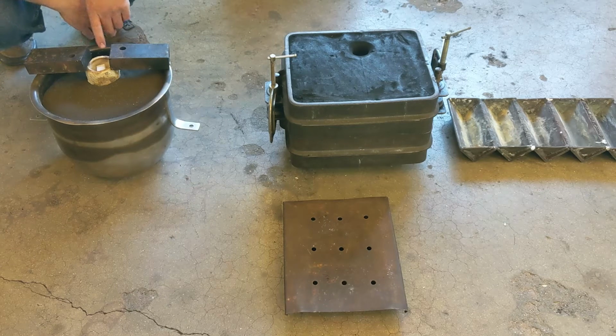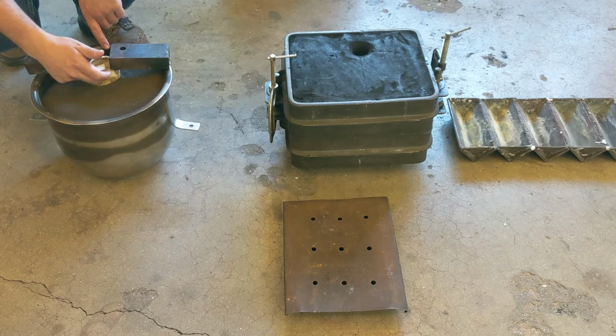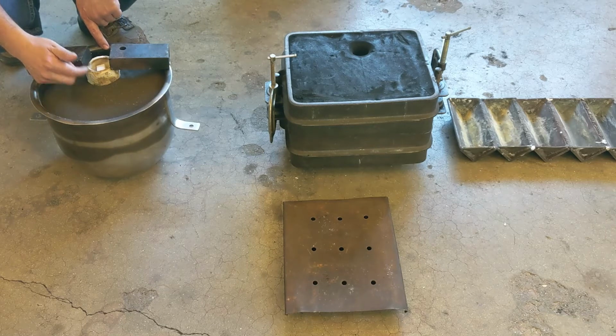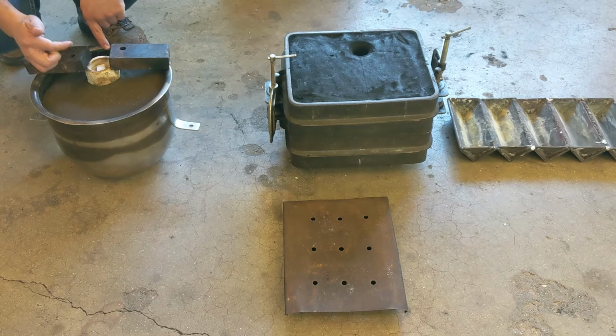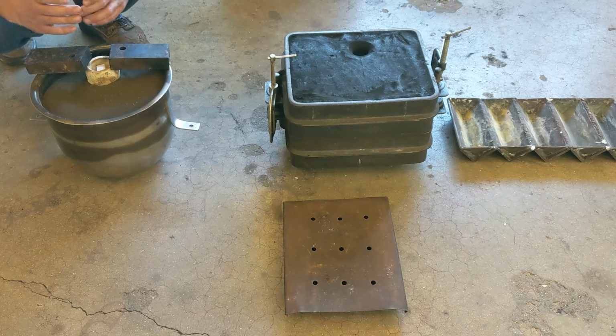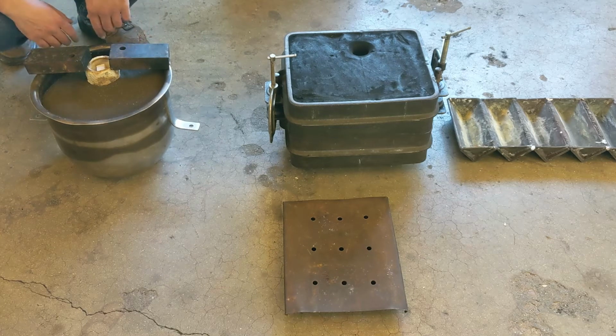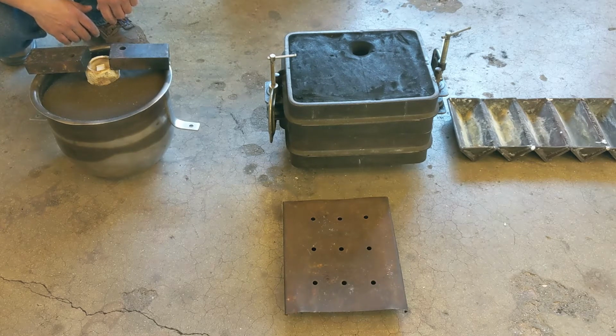So for the lost foam mold, this insulating sleeve that I talked about is going to fill with metal. Because the sleeve is so light, that will give it a tendency to lift when the metal gets inside. So I've added a couple pieces of ballast here, these two pieces of steel, to hold that insulating sleeve down so that it doesn't lift off when it fills with metal.